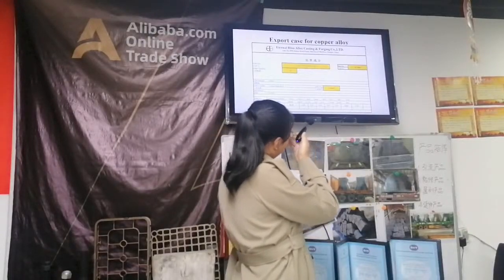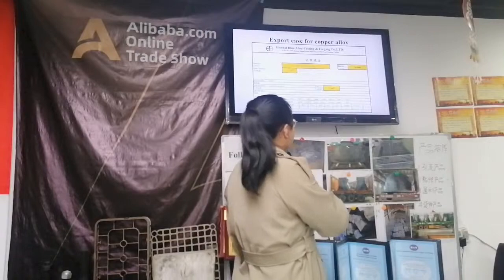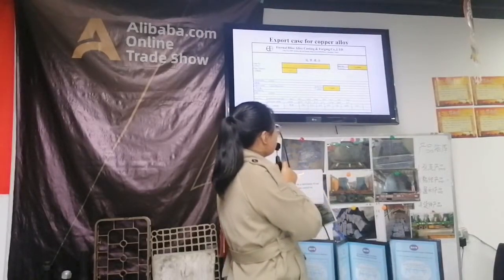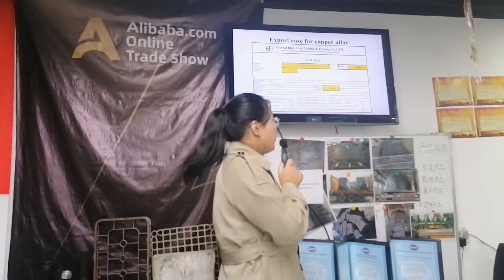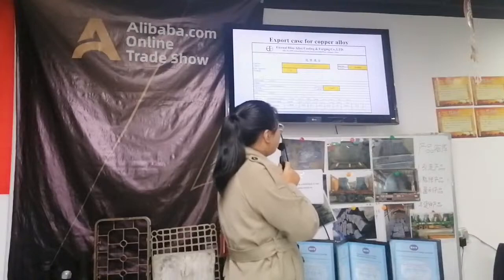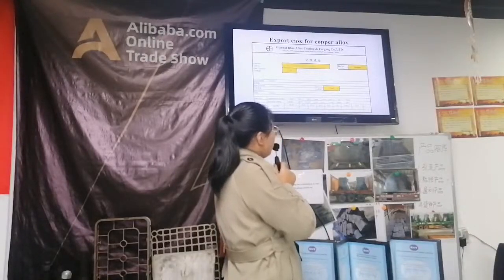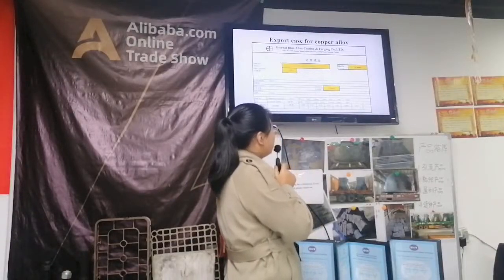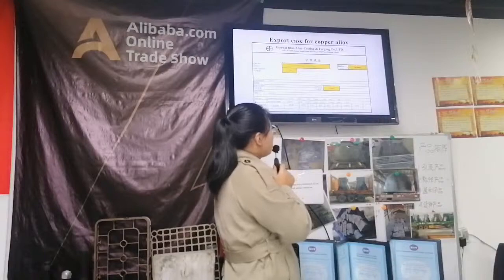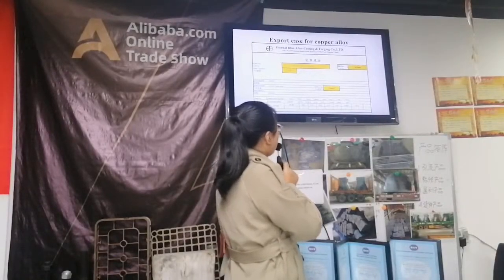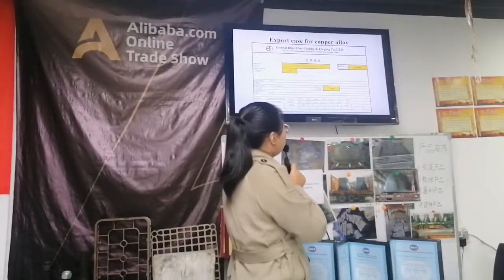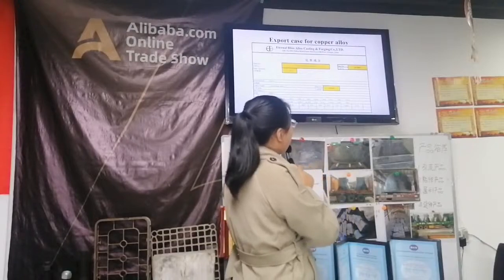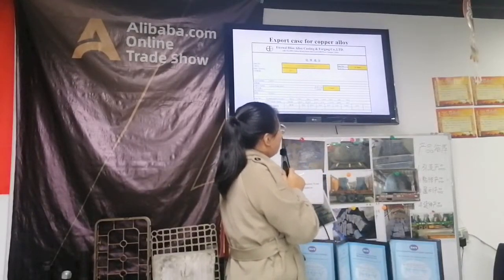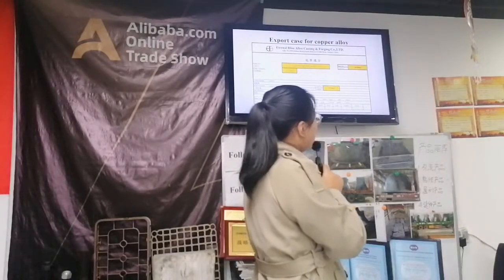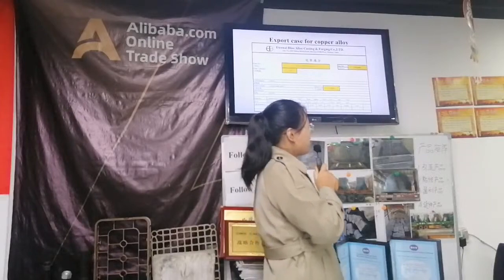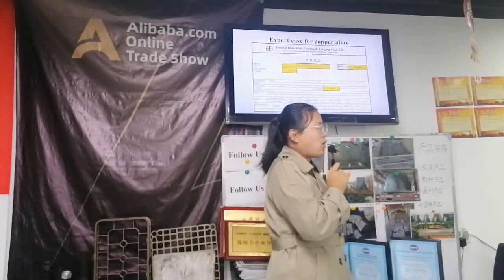Composition: for copper, the range is more than 78.6%, and the actual value is 78.684. For silicon, the range is less than 0.25%, and the actual value is 0.05. For aluminum, the range is 8.5 to 9.5%, and the actual value is 9.21. For iron, the range is less than 0.5%, and the actual value is 0.01.